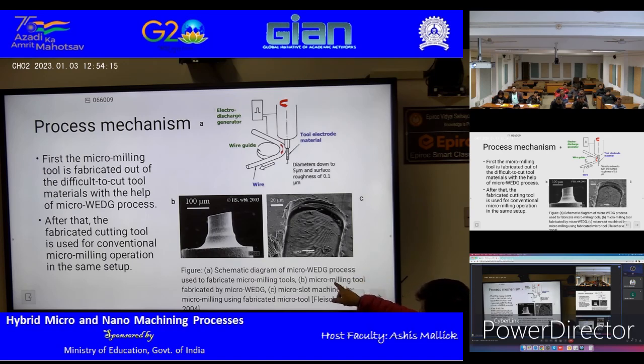So in the left side there is a micro milling tool, and as I mentioned, it should be doing the shearing operations, right? So they have that rake angle there, and you can use the micro wire electrodischarge grinding. So that means in the micro wire electrodischarge grinding, the benefit is from the block micro EDM. I talked about block micro EDM. So in the block micro EDM, you have a stationary block, then you're doing the turning operations, right? And there is a large contact surface, right? So there is a lot of sparking happening, and also there is some wear of the block. So if you don't use moving block, because of the wear of the electrode, you are going to end up with getting taper shapes, right? Then in order to get rid of that, you are using moving block micro EDM, but it's still a lot of surface. If this is the tool, the entire surface is where the sparking is happening, right?